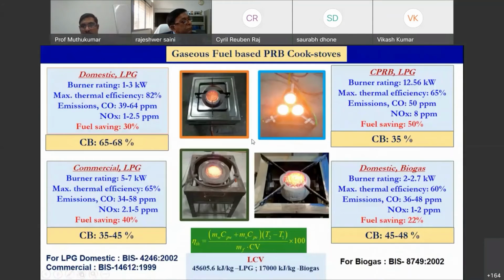We have developed several burners for various applications. You can see here the domestic cooking application, having power input of about 1 to 3 kilowatt. Here we got thermal efficiency close to about 82% in comparison with the thermal efficiency of the conventional burner of about 65%. Here we got about 30% fuel saving. And a commercial burner of about 7 kilowatt, here we got 40% fuel saving. Cluster burner of about 15 to 18 kilowatt, here we got 50% fuel saving.